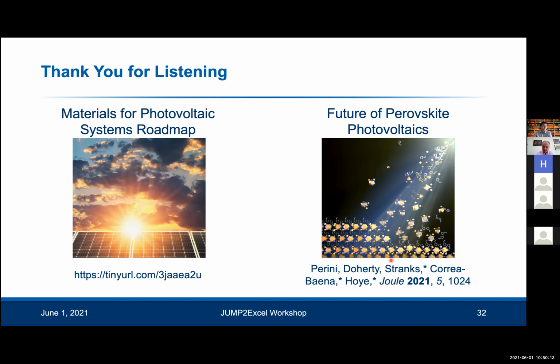I mean, you asked a good question. These standard tests were developed for the PV manufacturer, because in terms of the cost of production, PV manufacturers have to have one test that they do, which can satisfy the investor. So, the test I mentioned, 85 degrees C, 85% relative humidity, is a standard test that's been developed. And that came from outdoor testing that people have done on silicon PV. So these are accelerated degradation testing protocols for silicon PV, because nowadays people understand quite well what the degradation pathways are and what the various ways are in which you can stress a silicon device to test and predict whether it can last for 25 years.